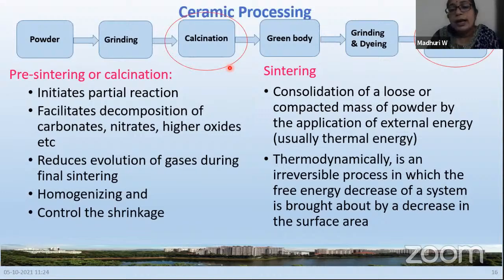Fine. So final sintering would facilitate the compaction of the material. It will give density to the material and form the structure. Fine. And this is all due to the thermal energy we are giving. And sintering can be defined as a thermodynamically irreversible process which is performed on a material. You cannot get back your zinc oxide and ferric oxide once you sinter them, or even calcinate them. After calcination also, you cannot get back your zinc oxide or ferric oxide. Once a heat treatment is done, it's an irreversible process. Fine. Similar to burning your cake. Once you burn your cake, you cannot get back your flour. Okay? In a similar way.